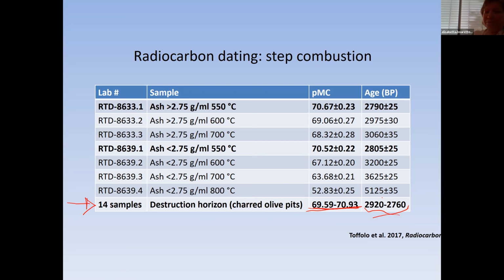So when we used our separation with the thermal decomposition, we obtained indeed the correct age for our layer, correct compared to the seeds.